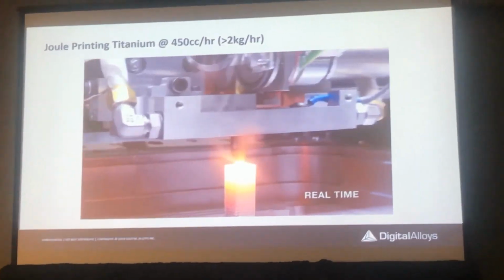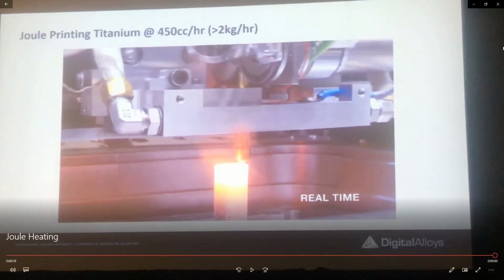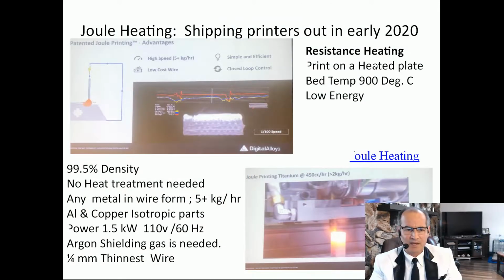And as you can see, this is a very fast process. It is a DED process, directed energy deposition, and high production rates of upwards of 5 kgs per hour is achievable with this process. And wire diameters as small as 1/4 millimeter also suggest that the parts produced from this are fairly accurate, and no subsequent heat treatment is necessary after the parts are produced. As you can see here, parts that are 99.5% dense can be used. No heat treatment is needed. Any metal in wire form, as I said, and low power inputs of about 1.5 kilowatts is used.